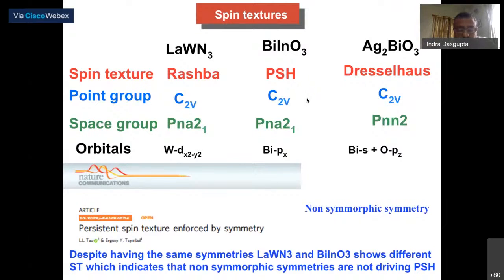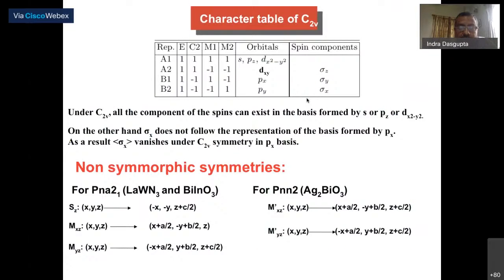So these orbital symmetries also have to be taken into account while deriving your so-called k·p model Hamiltonian or analyzing your Rashba-Dresselhaus model Hamiltonian. One can do a little bit of group theory to understand that. For example, orbitals like s, pz, x² minus y² are invariant under all C2v operations. As a consequence, they can accommodate all the spin components, sigma z, sigma y, and sigma x.